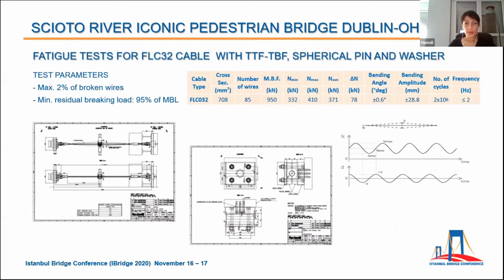Here we have the test parameters. On the FLC 32 cable, 2 million cycles with delta force of 78 kilonewton has been applied. At each cycle, the bending angle was minus plus 0.6 degrees. The maximum acceptable amount of broken wire is 2%. It means if the cable is made of 100 wires, only 2 wires could be damaged or broken after finishing the fatigue test.